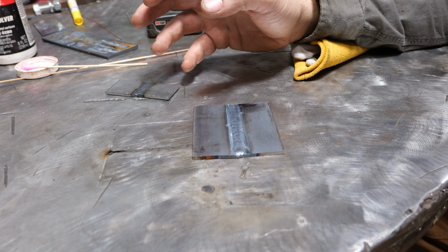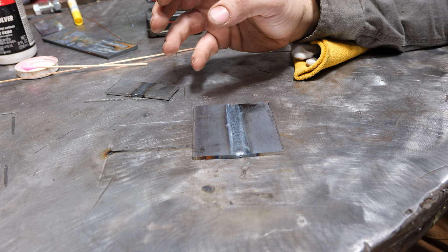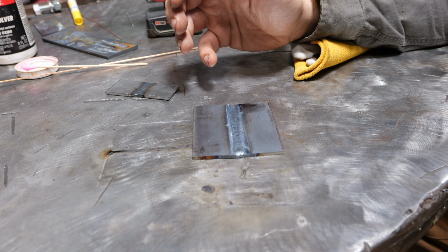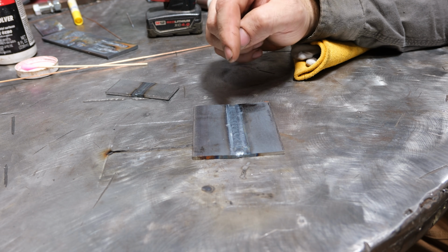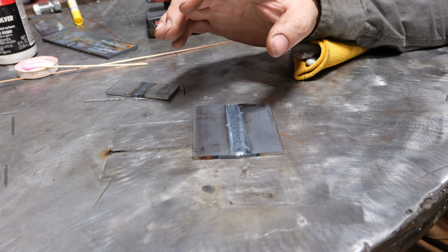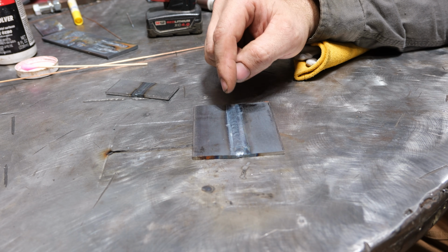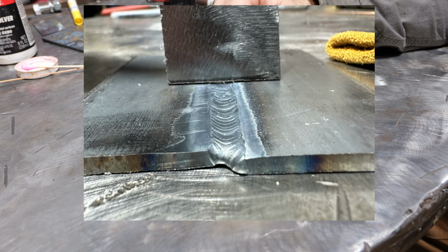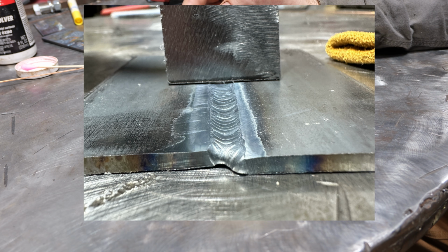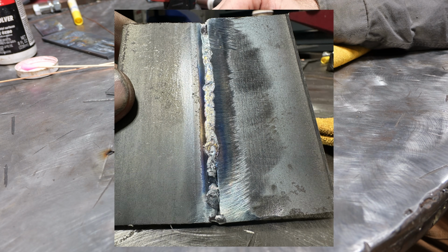Now, like everything on this channel, I tend to just make a weld and talk about it, and mistakes are very common, and this is a great example of what can happen. What I mean by that is I'll put a picture up right now, but even though I was successful in bridging the gap and I happen to have penetration and a pretty decent bead on the inside, it's not perfect, but it's decent. The face of it is more or less underfilled. And this is very common when you're trying to bridge a gap, that you actually underfill it.